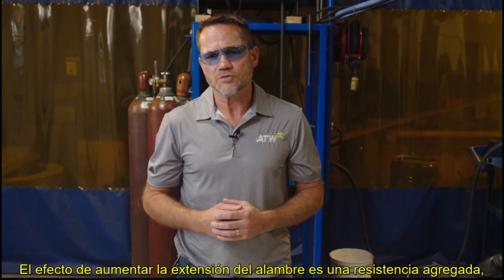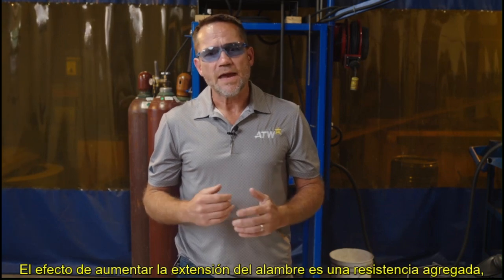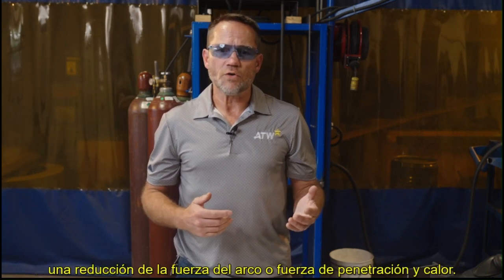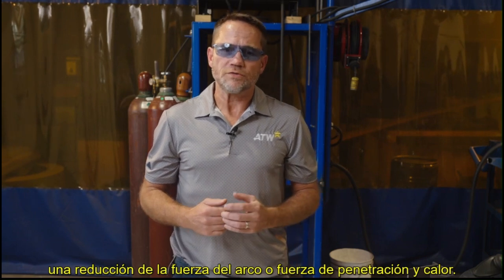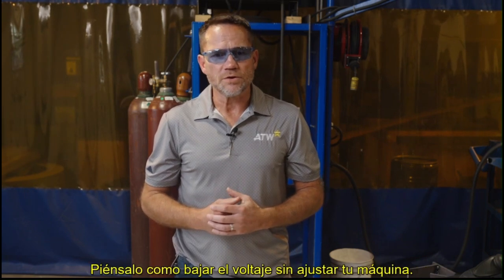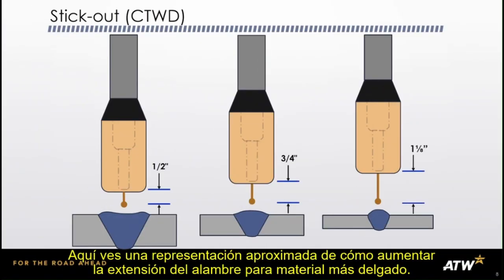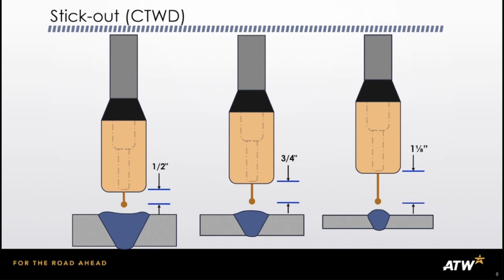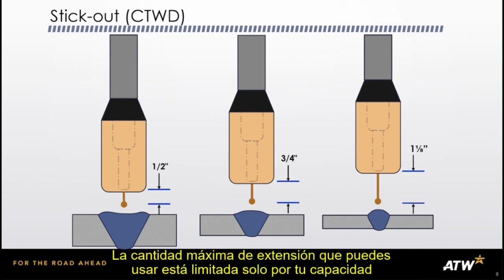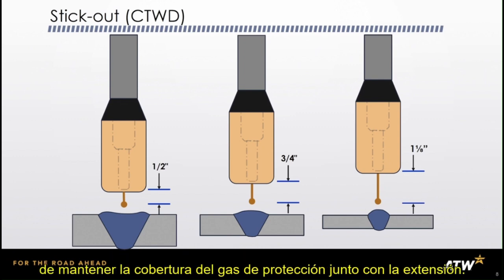The effect of increasing stick out is added resistance, a reduction of arc force or penetrating force, and heat. Think of it like turning down the voltage without adjusting your machine. Here you see a rough depiction of how to increase stick out for thinner material. The maximum amount of stick out you can use is limited only by your ability to maintain shielding gas coverage.